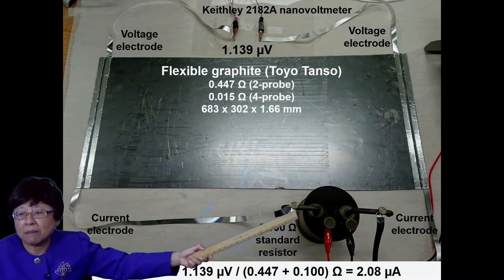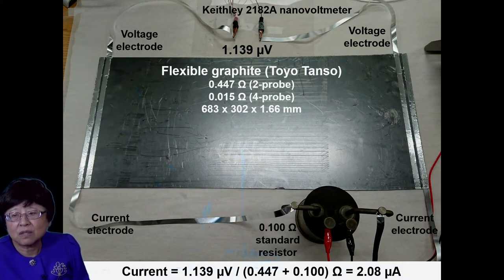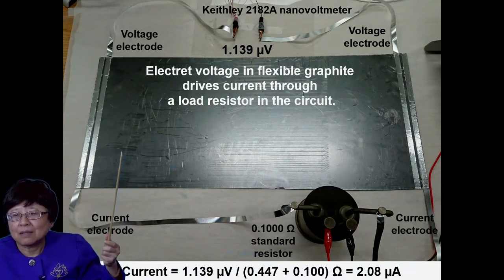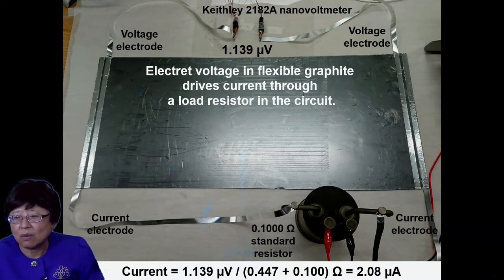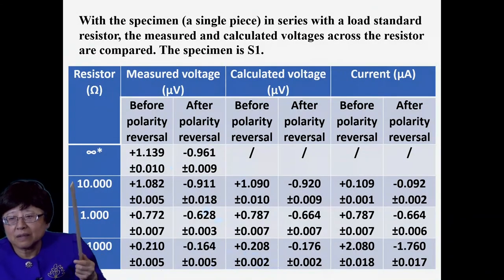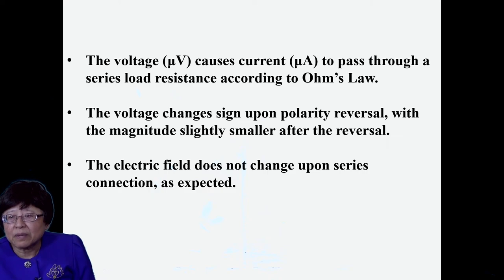And we find that here, this is a standard resistor, so we can measure the voltage across that standard resistor, thereby obtaining the current through this whole thing. And we find that it's all in accordance with Ohm's law. Okay, that is, the graphite simply drives the current through the load resistor in the circuit in accordance with Ohm's law. And we've tried different load resistances, shown here, and they all jibe with Ohm's law. The voltage causes current to pass through a series load resistance according to Ohm's law, but it's just microvolt and microamp. The voltage changes sign upon polarity reversal, with the magnitude slightly smaller after the reversal.